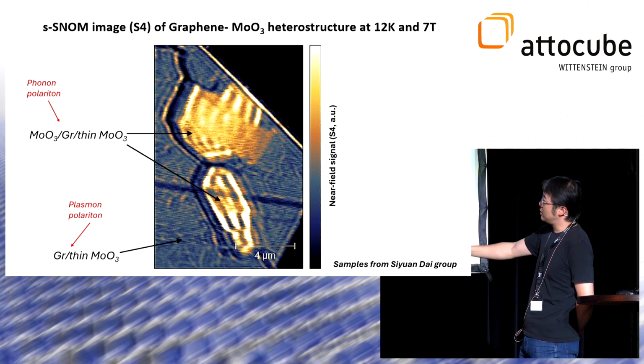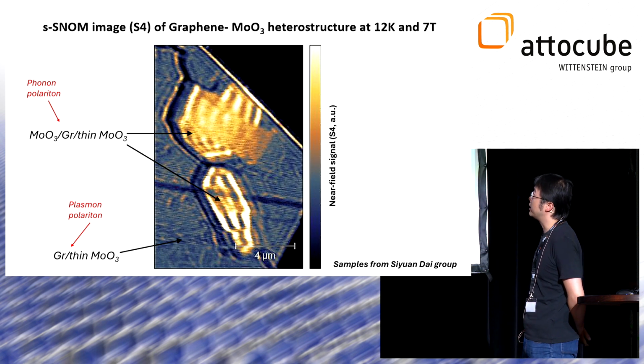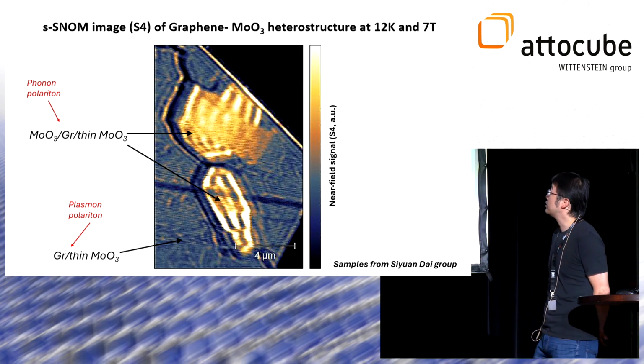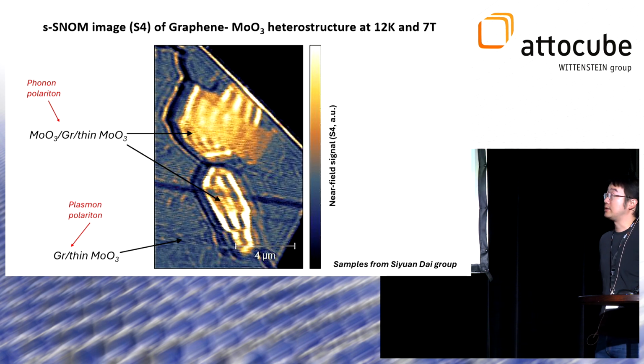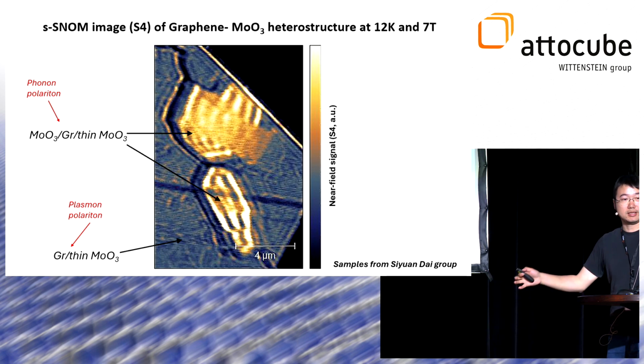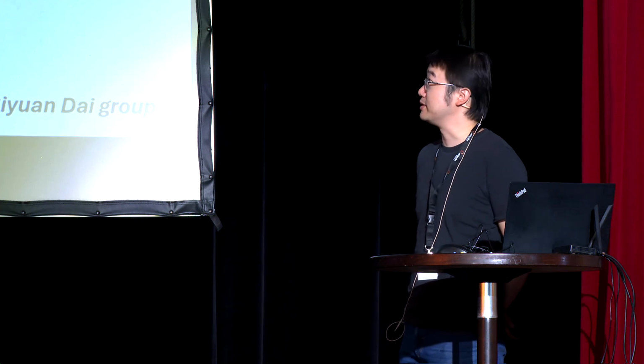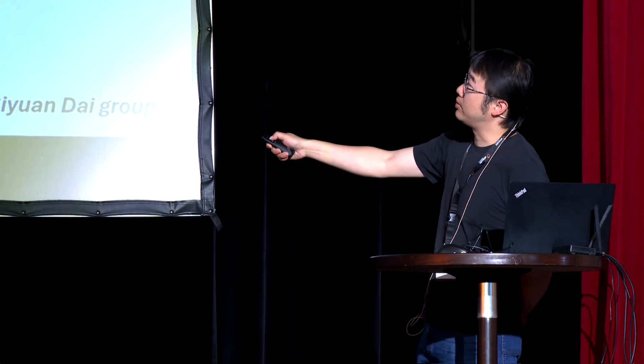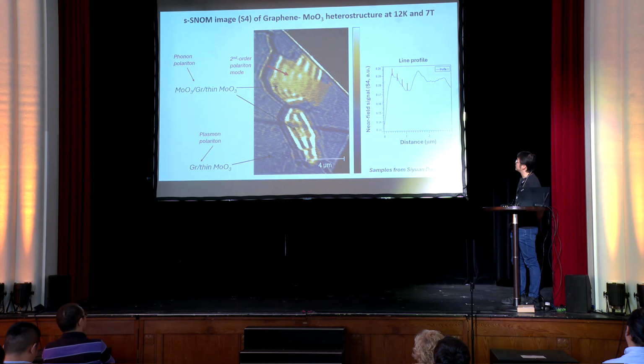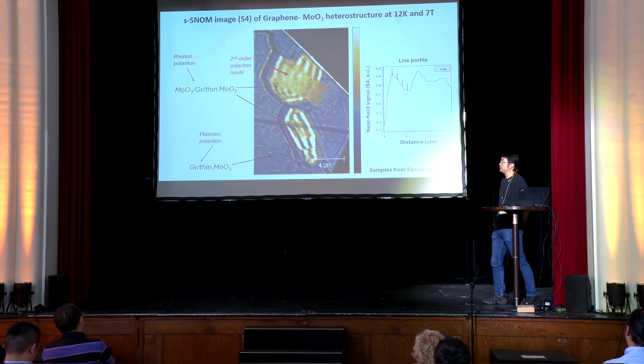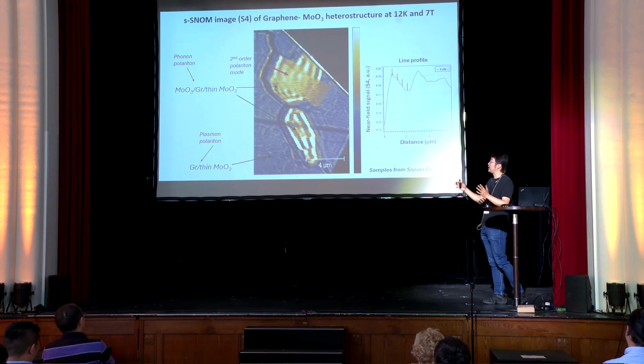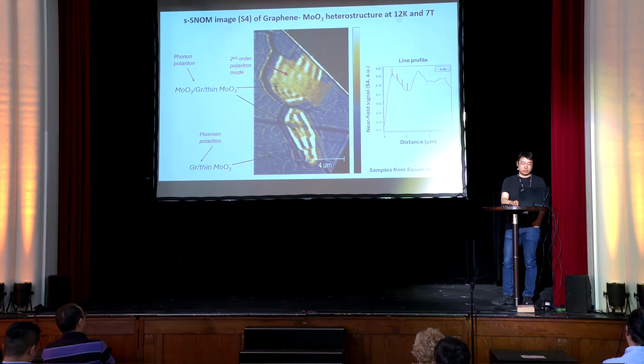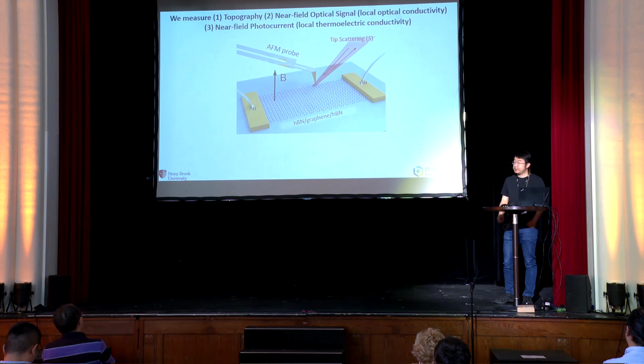We can also observe the plasmon polaritons in graphene, right? You can see the image quality is quite good in general. Of course, you might ask, what's the magnetic field doing here? Not much in this case, but I'll show you what it can do in other cases. We also see the second order polariton mode, which you cannot see on this screen, but I just plotted here. So over this 10, 20 micron length scale, you can still see 100 to 200 nanometer polariton waves at this low temperature and high magnetic field. So I would say this is quite nice.